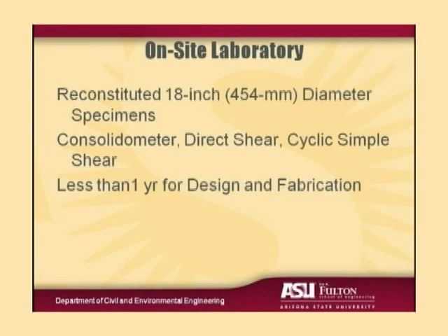Well, we took that waste and we did some testing. We constructed an on-site laboratory to test 18-inch diameter, 454 millimeter reconstituted samples. Our original intent was to try and recover undisturbed samples. When our estimated cost of the equipment got to about $500,000, and we still hadn't figured out how we were going to extrude the samples from the stainless steel cylinders into the testing devices, our client said, come up with a better idea.